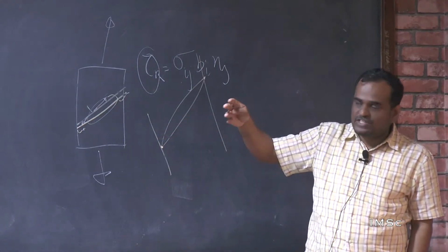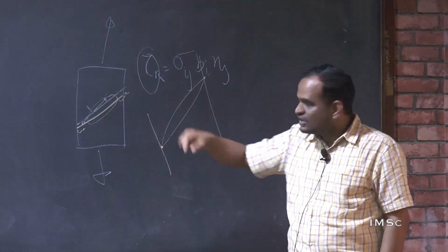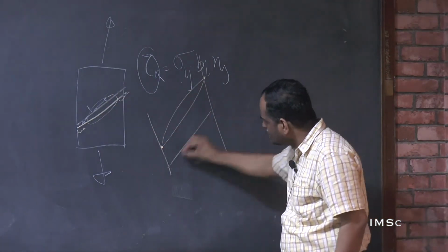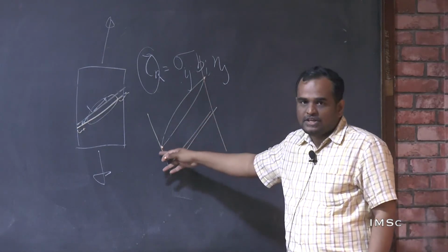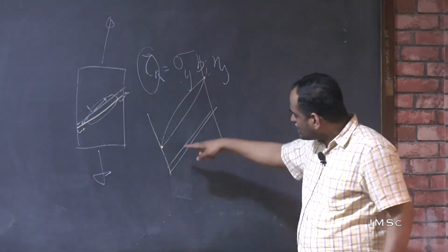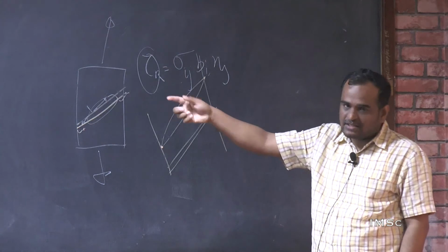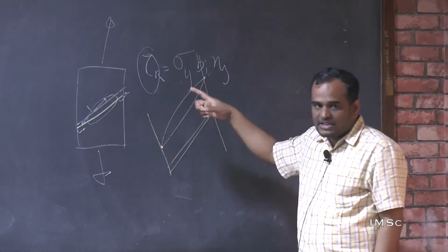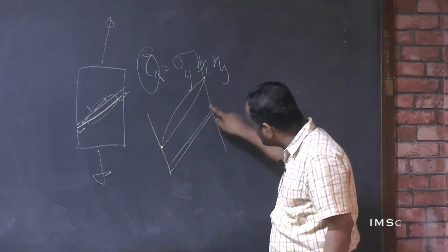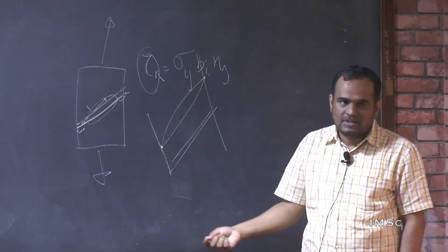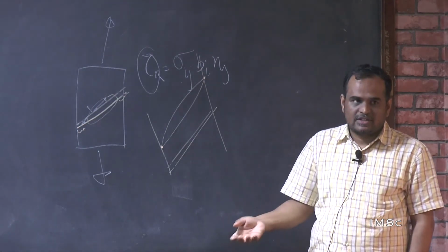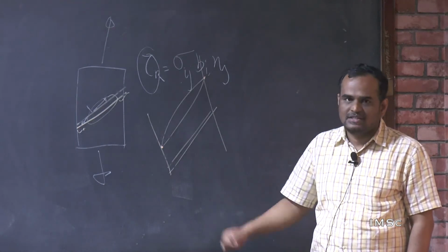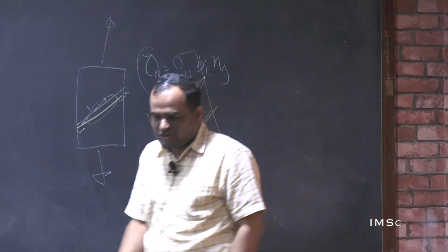One of the common features, in fact in one of the earlier micrographs you have seen, is that twins do not appear as two flat lines. That is a numerical approximation. It is more probable that you will see lenticular shaped twins, and that shape has to do with the fact that the local resolved shear stress is negative, which impedes the growth of the twin. That was the first time we showed numerically, without explicitly accounting for it, that it simply comes from the local interactions that take place. Okay. So I have too many slides, but I will see what I can do.